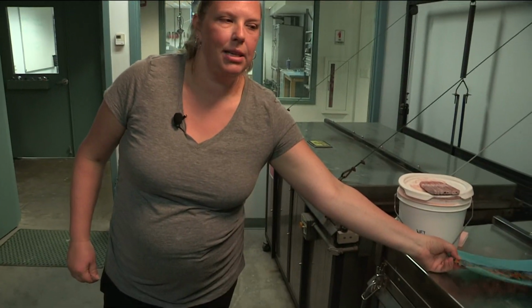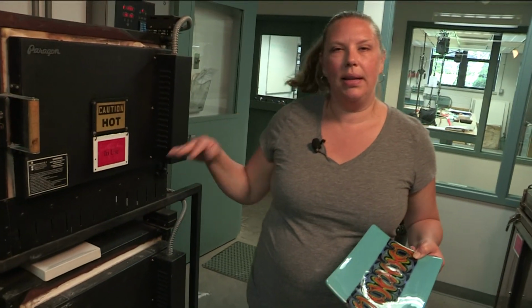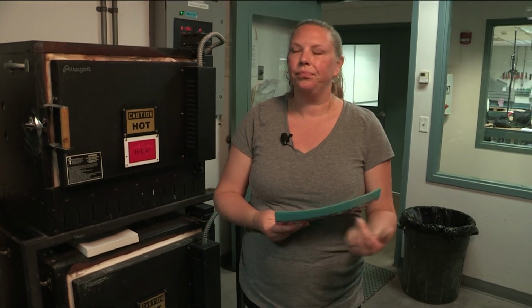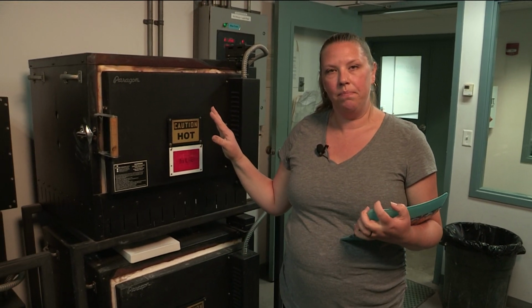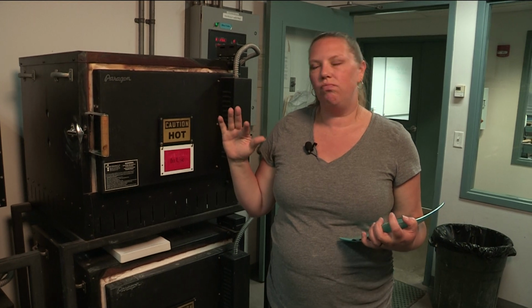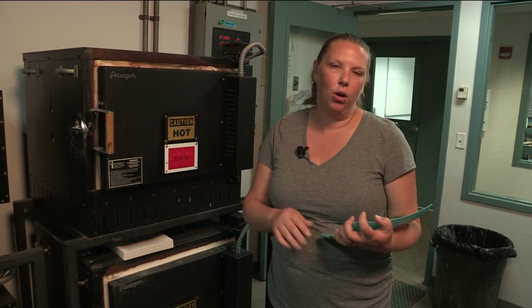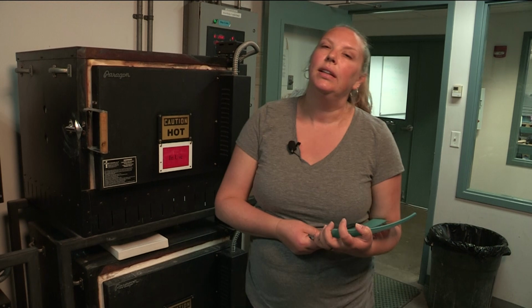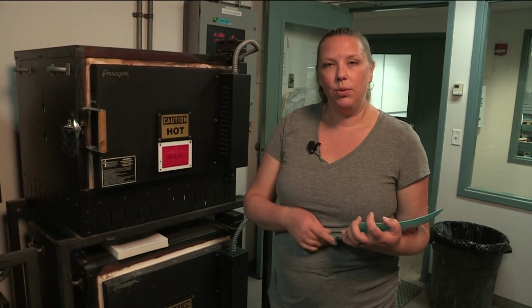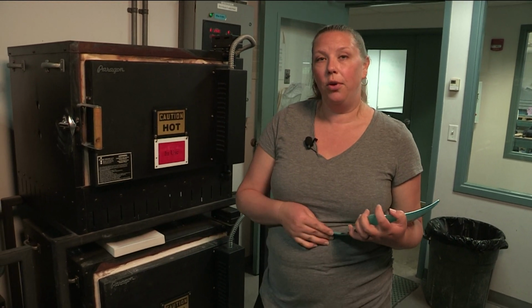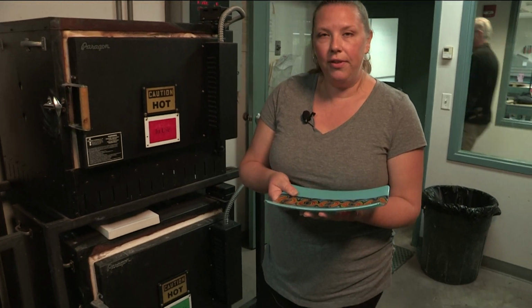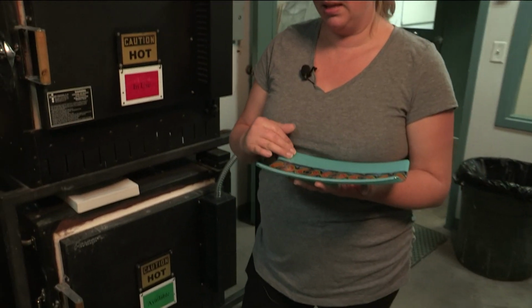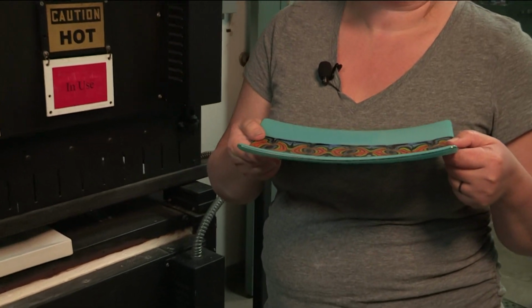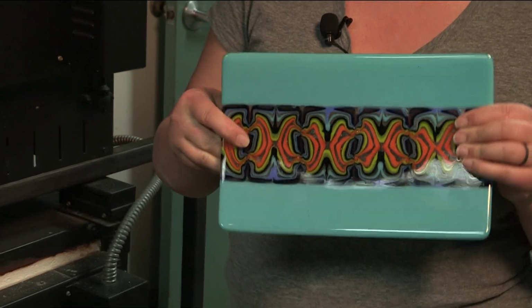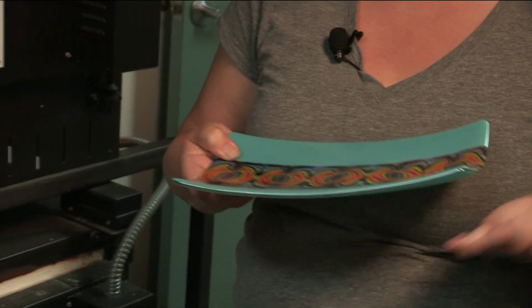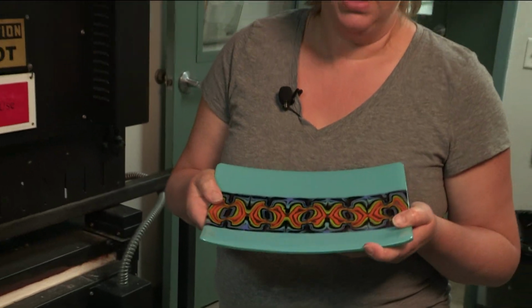But we'll end up putting the glass, setting it on top of the mold. And then I would reprogram the kiln so that it's going to come up to only about 1290 Fahrenheit, just about 1300 degrees. So then the glass will actually take the shape of the form, and when you're all finished and you have to wait again for it to come out of the kiln, you'll get your final piece. And so your final piece will have taken the shape of that mold, and it's a three-dimensional form. So there you have it.